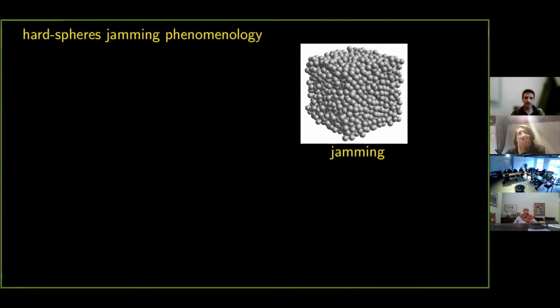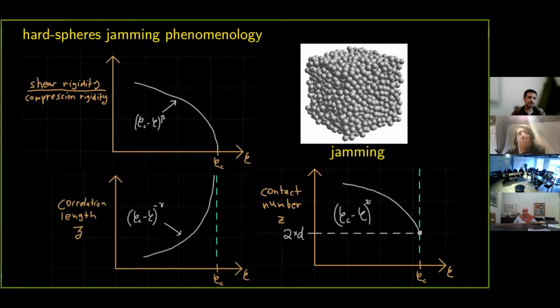Now I'm going to jump to the jamming problem. Again, consider your canonical hard sphere system. The hallmark phenomenon that takes place in these systems when they're compressed is that the ratio of the shear to the compression rigidity vanishes at the critical packing fraction with some power law. There is a diverging correlation length at that transition, diverging at this critical packing fraction phi c. Another remarkable phenomenon is that if you count the number of interactions, the number of pairs of particles that are bouncing onto each other, that number approaches 2 times the spatial dimension exactly at the critical packing fraction phi c.